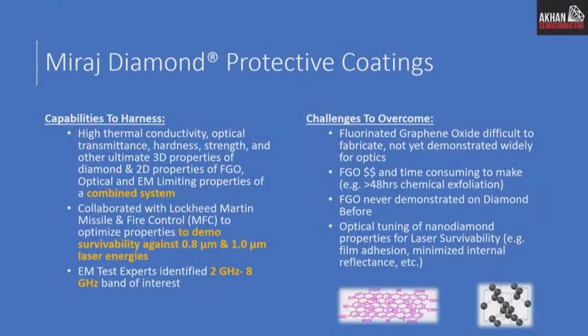Some challenges that we had to overcome: fluorinated graphene oxide is obviously very difficult to fabricate, it being a new material, particularly in optics. The current method of producing it, though, is very expensive. It takes a long time to chemically exfoliate this material, over 48 hours inside of a chamber, actually to reduce it. And this has never been demonstrated on diamond before. Relating to the FGO side, we still have the problem of optimizing the diamond, particularly for this laser energy. So that is exactly what we set out to do, and thankfully we had a video and camera with us during the fabrication part of this, and I'm happy to present that to you now.